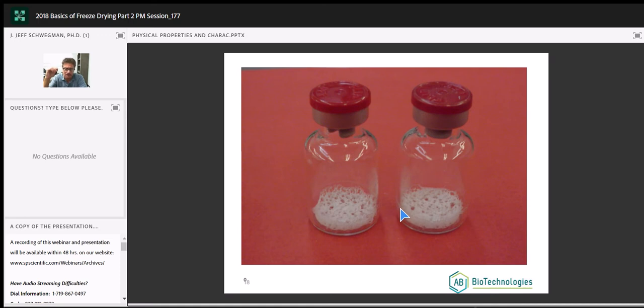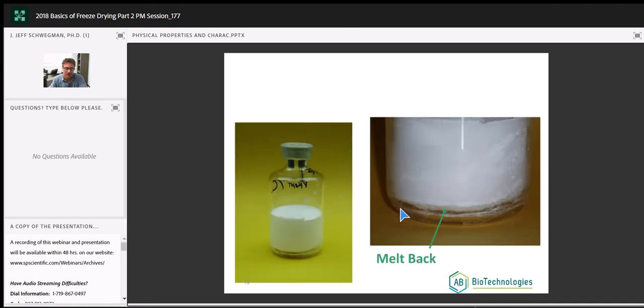Edge effect is where the vials see a slightly warmer environment on the outside. In this particular case, these vials got slightly too warm, started to get too close to the glass transition, and partially collapsed. So that's what we would call a partial collapse. This one's melt back, like I mentioned. Sometimes it will manifest itself as a dissolved ring of material around the bottom of the vial. Again, we did not stay long enough in primary drying, ramped up to secondary, and the ice that was on the bottom went ahead and melted and then dissolved some of the cake at the bottom.